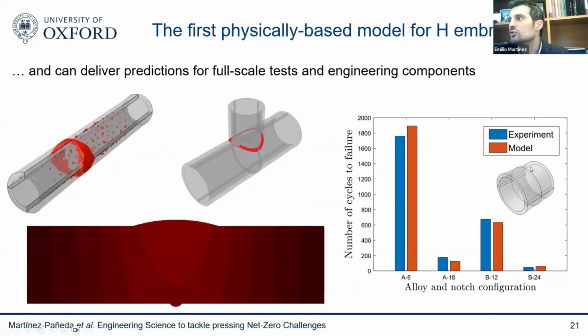And we have compared our predictions not only with lab academic experiments, but also with real full-scale experiments. These are pressure vessels, and you can see that we can capture the number of cycles to failure quite nicely. So this is an opportunity because these models, again, not only bring us new physical insight, but this idea of virtual testing that we use quite significantly in automotive and aeronautical industries, we can bring it to hydrogen-containing environments for energy and other applications. So that's the promise, basically.